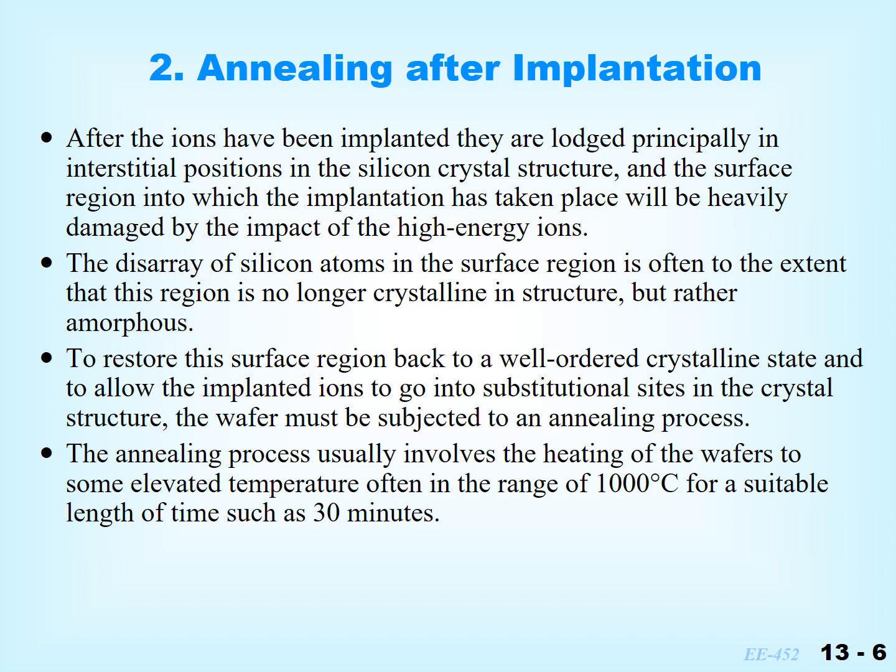So to achieve that well ordered crystalline structure back, annealing is the process used, and this is done at around 1000 degrees Celsius for about 30 minutes. Okay.